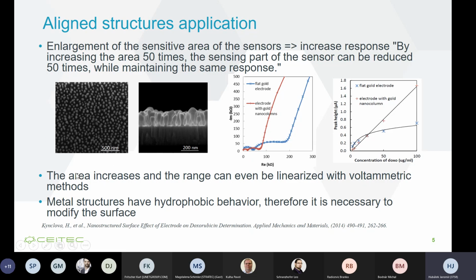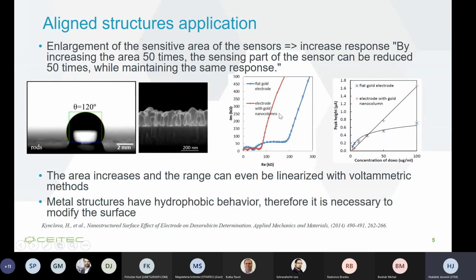Here you can see some of our results. They are already old results. We used nanorods on the surface, and we characterized these structures using electrochemical methods, which you can see here. It was impedance spectroscopy and voltammetry. A flat and a nanostructured electrode were compared here, so you can see some benefit. It was really in the sensitivity, and the effect of enlarging the area is clear here.